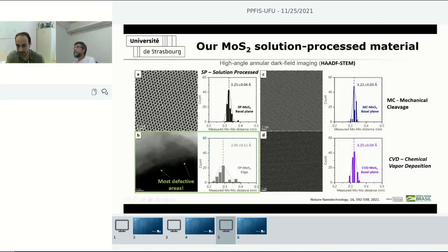Let me go back to the presentation. So the vacancies are more at the edge, not in the inner sides. No, not in the basal plane. Do you see my screen? Yeah. Okay, so let's talk about the figures on the left. Here we have the data from high-angle annular dark field imaging for the solution processed material of ours. This is its basal plane. This is its edge. Here there are no defects. The defects are here on the edge, and the molecules functionalize these defects.